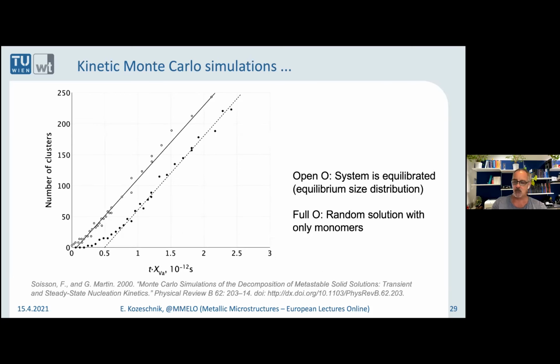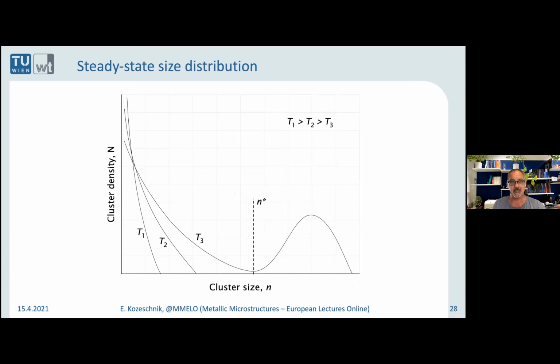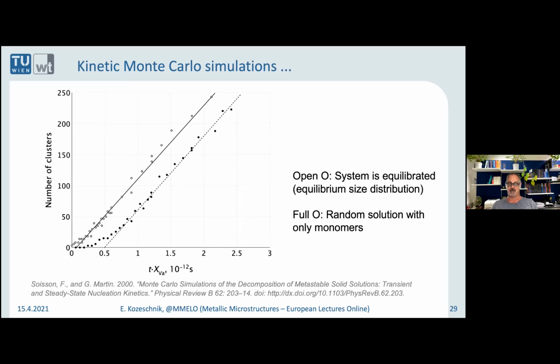And this is exactly what people consider as time-dependent nucleation. So at time t equals 0, there will be no nucleation yet because the clusters are not yet large enough if you quench from higher temperature. It would take some time, and this incubation time is related to the time it takes to produce the first clusters of sufficiently large size.